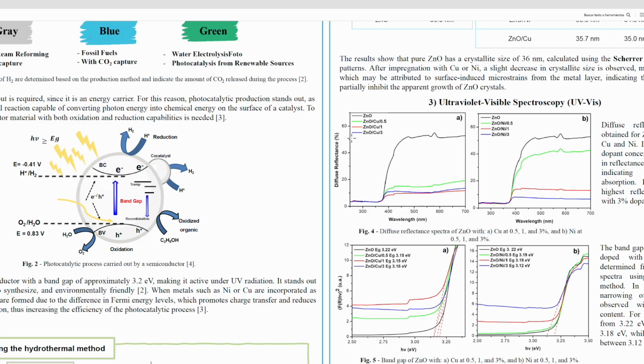In the UV-vis spectroscopy, we were able to measure precisely in test A and in graph B the diffuse reflectance of our zinc oxide, where we can see that in the pure part of the material, it reflects everything that is incident on it and shows a drop at the wavelength that zinc oxide absorbs, as reported in the literature, which is in the ultraviolet.